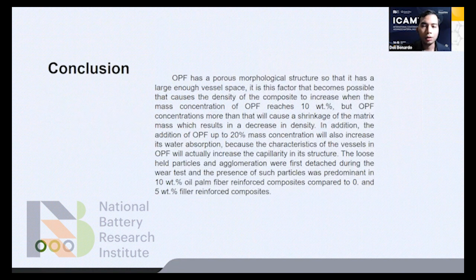So from our research, we conclude that, as we know, OPF has a porous morphology, so that it has a large enough vessel space. OPF concentration more than that will cause a sinking of the matrix mass, which results in a decrease in density. In addition, the addition of OPF up to 20% mass concentration will also increase its water absorption because of the vessel in the OPF structure. The loose particles and agglomeration were first detected during the wear test, and the presence of such particles was predominant in 10 weight percent of fiber reinforced composite compared to 0 and 5 weight percent fiber reinforced composite.